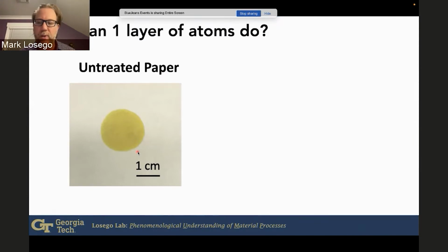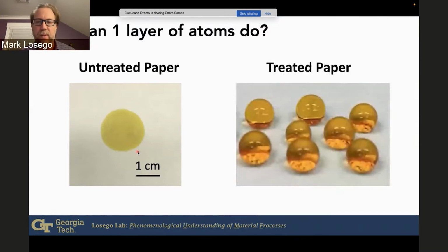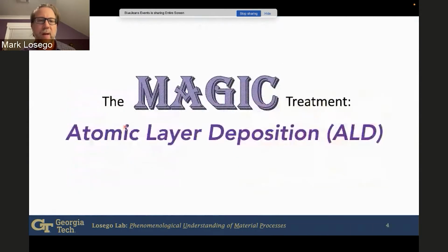And this is on untreated paper, but if we modify it with this one layer of atoms, with these treatments that we do, we're able to convert that paper to being hydrophobic, or repelling of water. And we see the water, these yellow dyed water beads, bead up on the surface of the paper rather than wick and wet into the paper itself. So there's a lot of things that you can actually modify with just a single layer of atoms.